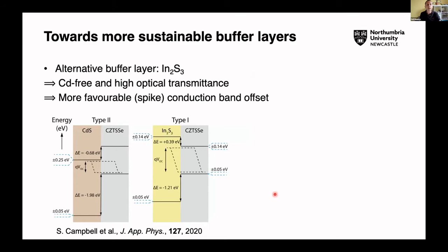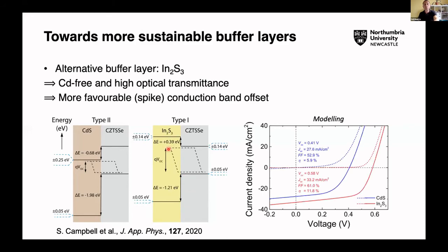One of the things that we want to do, and we've heard a bit about this today, is look at the buffer layer and how do we replace cadmium in these devices. And we've done some simulations looking at cadmium sulfide versus indium sulfide, and indium sulfide has a slightly more favorable conduction band offset, which should help with the open circuit voltage. And when you do the drift diffusion modeling, you can see that in theory the indium sulfide system should work quite well, not just from the band alignment but also from the JV data.